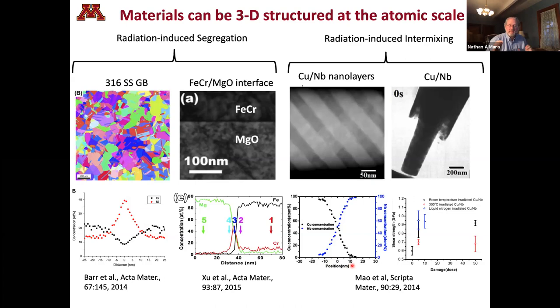Well, if you do a similar experiment to what we had seen earlier with these micropillars, and you irradiate the material at liquid nitrogen temperatures, that means you mix the material and then it's quenched in. It doesn't have a chance to phase separate, which is what it thermodynamically wants to do. And so you end up being left with these compositional gradients. As you notice here, it increases the shear strength of the interface by about a factor of two or so, relative to other materials where they remain phase separated after irradiation. So what we know from the literature without doing other experiments is that when you get these 3D interfaces, the interfacial shear strength goes up. And we know that's one of the key parameters for mechanical deformation.